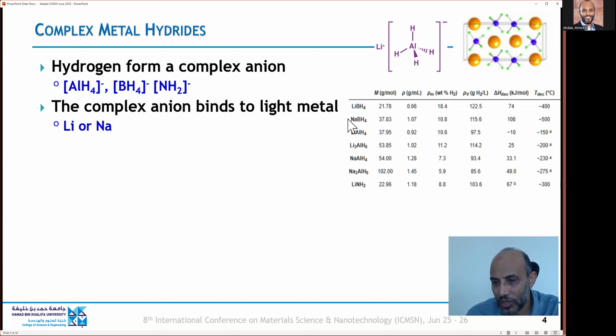So we have a variety of these metal hydrides, and they have storage capacity from 6 to 18 weight percent of hydrogen, and volumetric capacity close to 100 or sometimes higher than 100 kilogram per meter cube of hydrogen. And the challenge is usually associated with the desorption temperature. The onset of the desorption temperature is quite high. Most of them are above 200 degrees, and only lithium aluminum hydride has a moderate, or relatively lower temperature, about 150 degrees. The desorption energy is also significant for most of them. The lithium aluminum hydride has a lower desorption energy of about 10 kilojoule per mole.